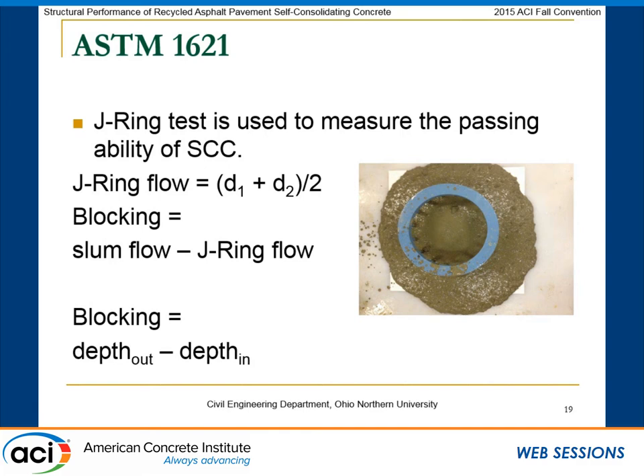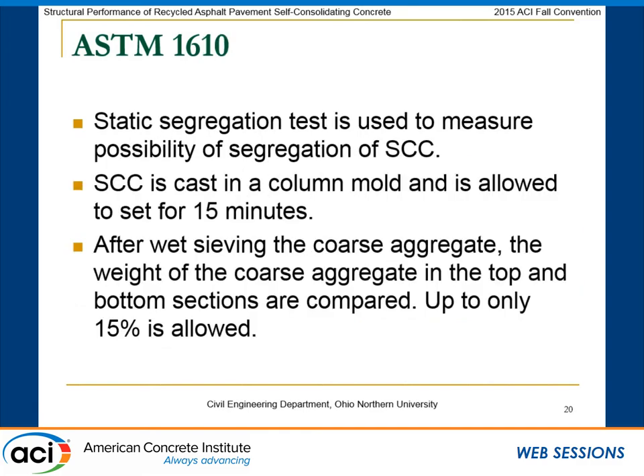You can also measure the blocking by measuring the depth from the top of the ring to the top surface of the concrete inside the ring and also outside of the ring. That can also give you an indication if you had any blocking due to the reinforcement.